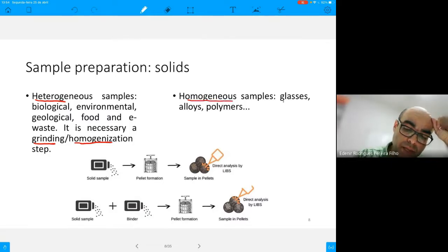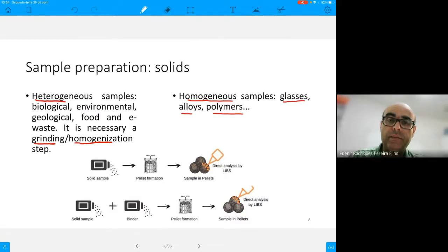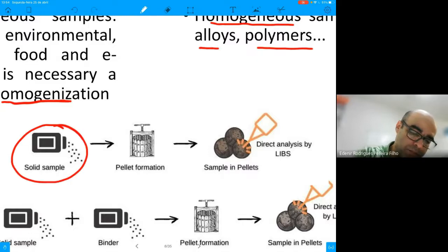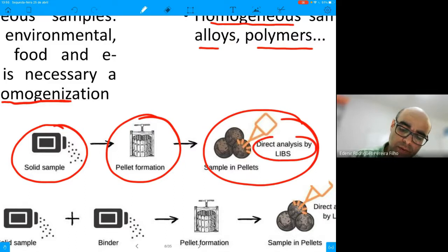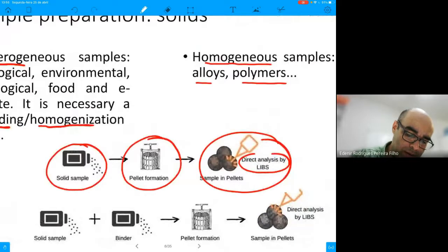With homogeneous samples like glasses, alloys, polymers, we can present the sample directly to the instrument. And in the majority of the cases, we have a solid sample. We can perform a pellet. We can have a pellet. And with this pellet, we can also directly present this for the laser. In some cases, it is necessary to use a binder. For example, polyvinyl alcohol, for instance. We can have a binder in order to obtain a pellet, a more solid pellet for the samples.